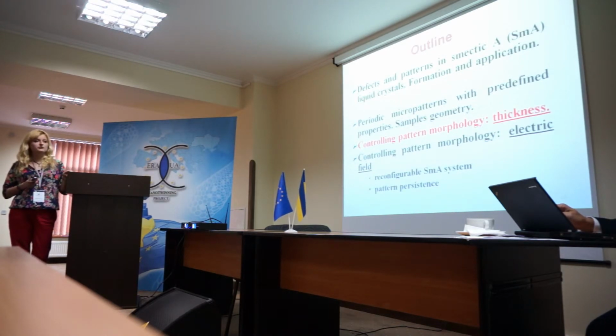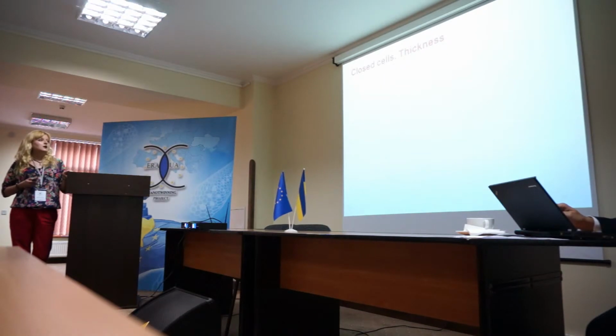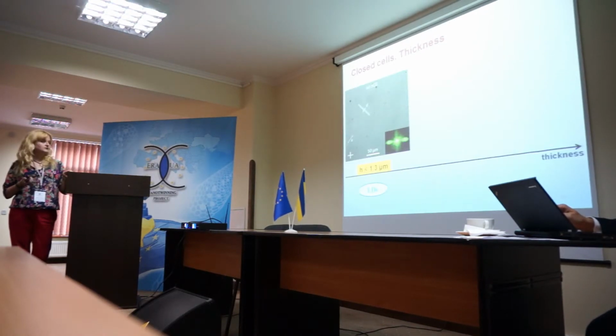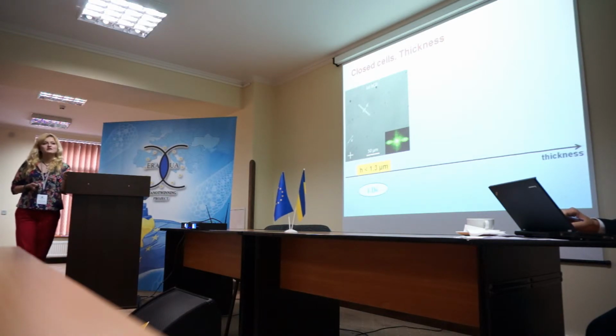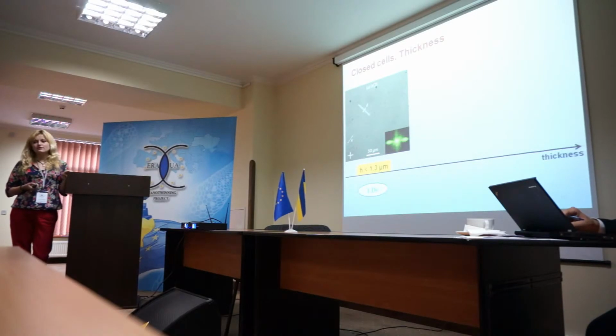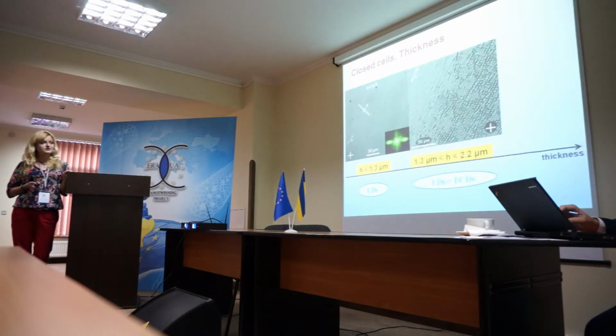Controlling the pattern morphology: thickness. Our measurements have revealed that for a thickness of the smectic liquid crystal smaller than 1.3 micrometers, we had only one-dimensional linear defect arrays. When we further increase the thickness, linear defect arrays coexist with patches of hexagonal focal conic domains.